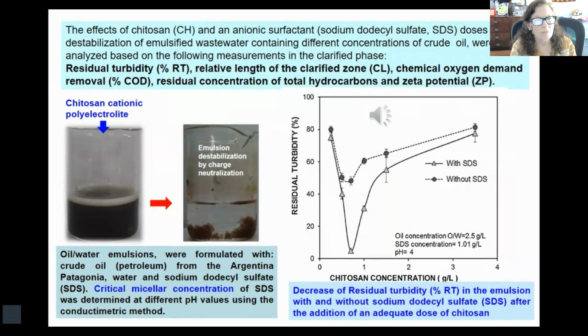Oil-water emulsions were formulated with crude oil, petroleum from the Argentine Patagonia, water, and sodium dodecyl sulfate, that is an anionic surfactant. We can see that the addition of chitosan, that is a cationic polyelectrolyte, produced the destabilization of the emulsion by charge neutralization. At the right, we can see the decrease of residual turbidity in the emulsion with and without sodium dodecyl sulfate after the addition of an adequate dose of chitosan.